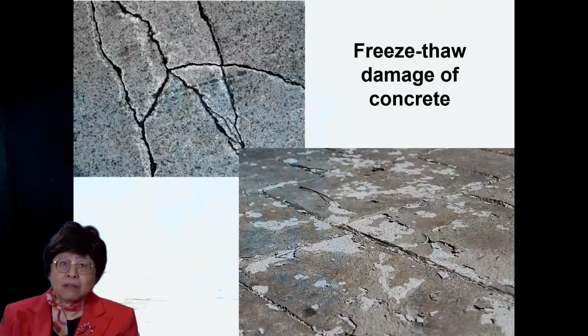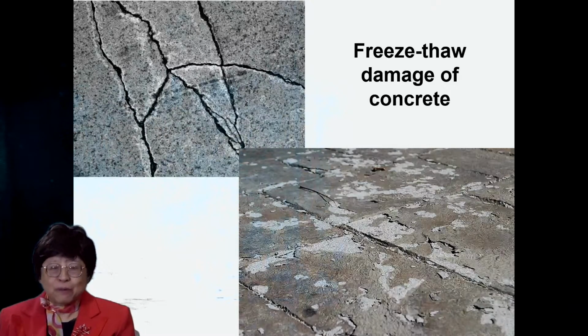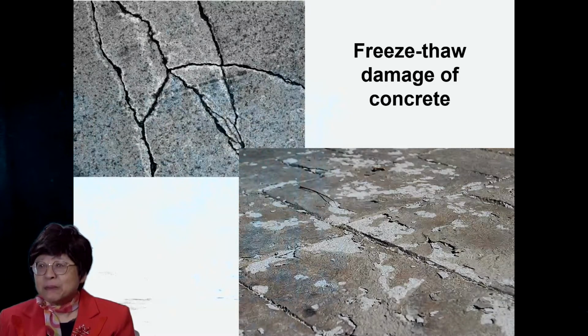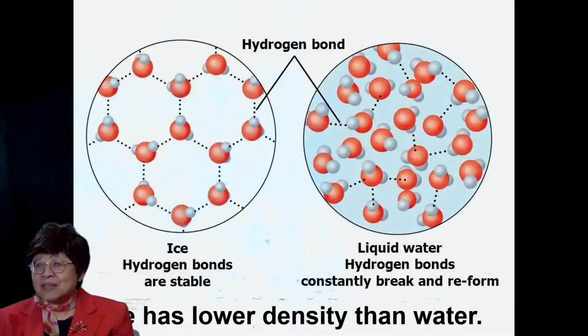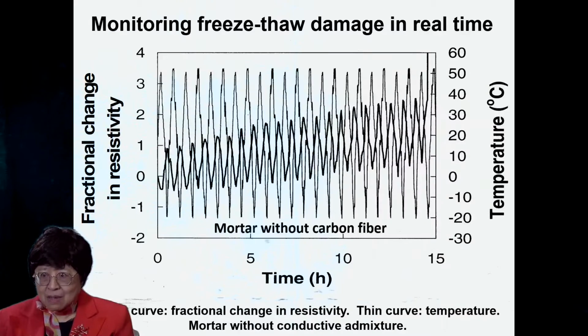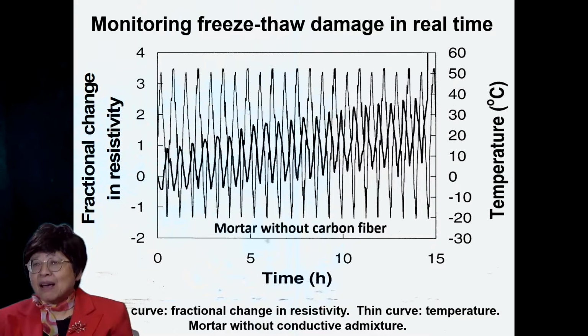Freeze-thaw damage is a trouble for concrete structures such as pavement. And this is because ice has lower density than water. And we have been able to monitor the freeze-thaw damage in real time by resistance measurement. And the thin line is the temperature going below 0 degrees C to above 0 degrees C. And the thick line is the resistance.